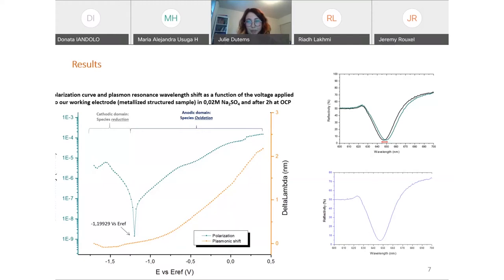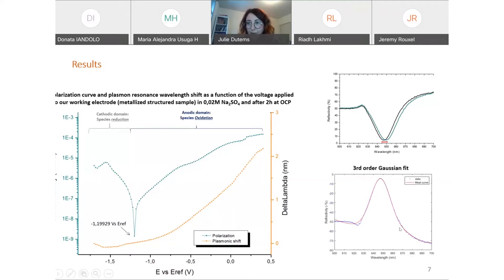For each spectrum that has been acquired, we have reversed it and made a third order Gaussian fit in order to have a mathematical equation, and hence it is possible to retrieve the resonance wavelengths with a huge precision. So what's happening on this curve? With those low potentials, we are in what we call the cathodic domain, which means we have species reduction. My metallic samples, my aluminium samples, when they were in the air, a passive film naturally appeared to protect it from oxidation. And with those potentials, this passive film has been reduced. And it is possible to observe it thanks to surface plasmon resonance.